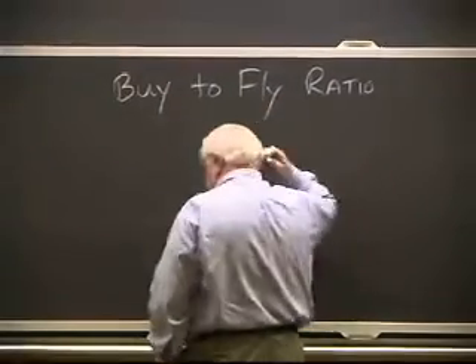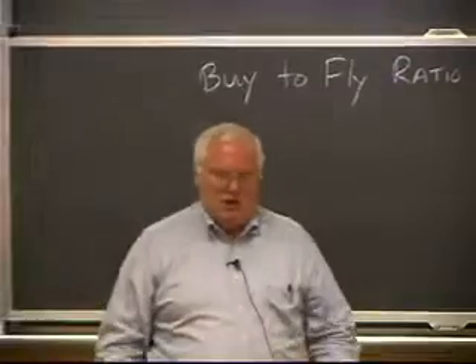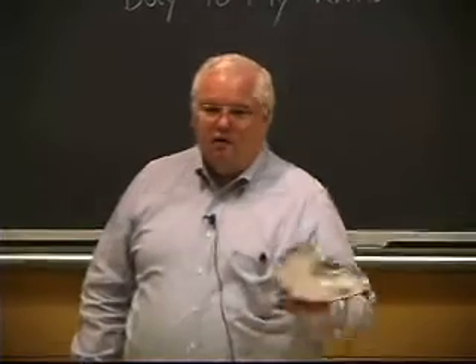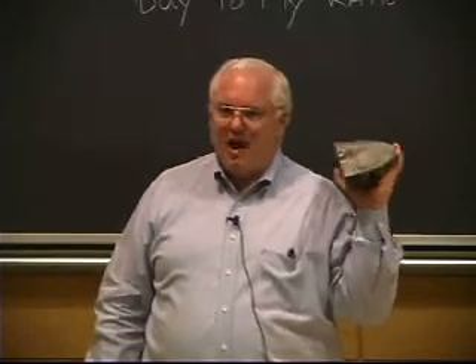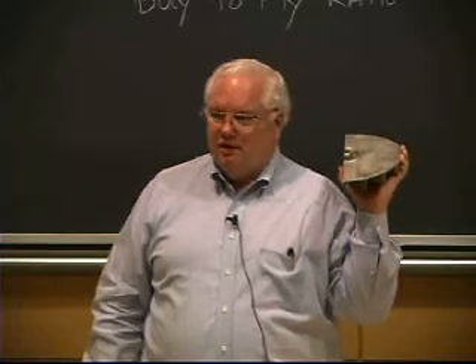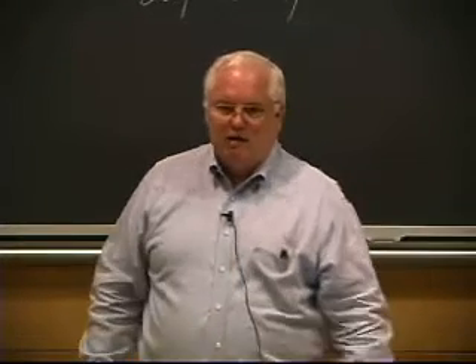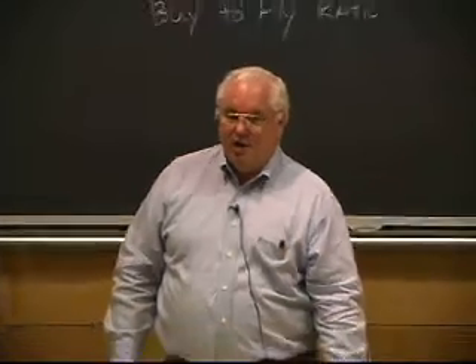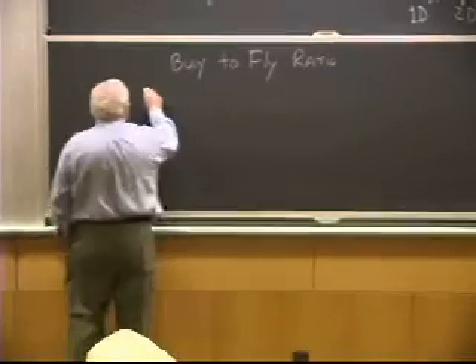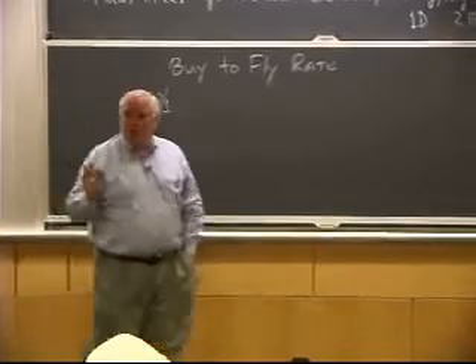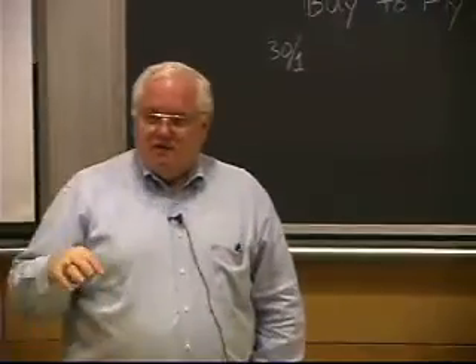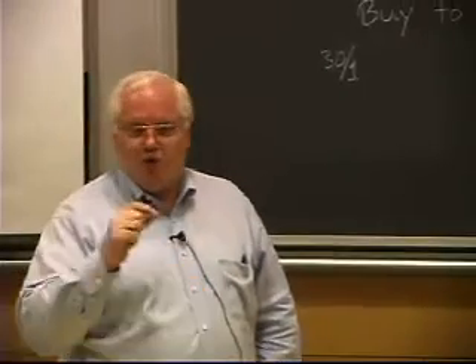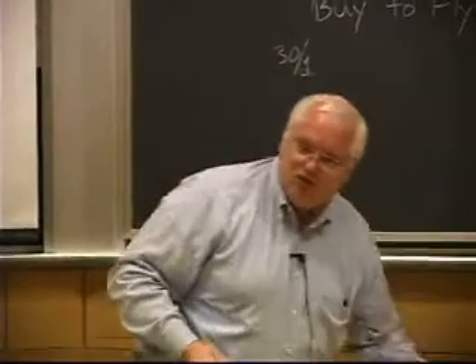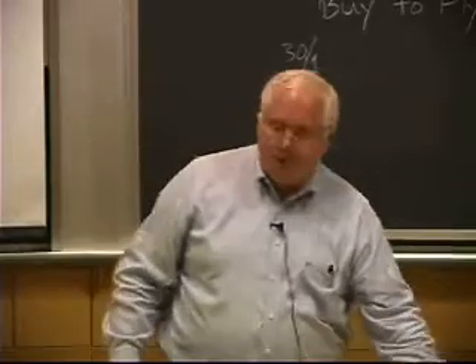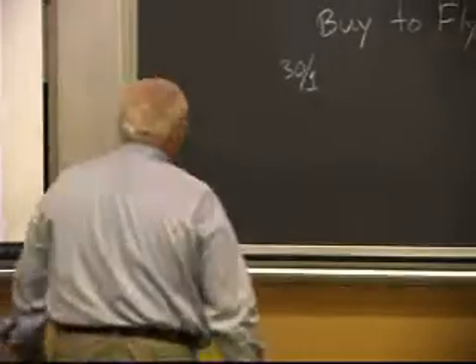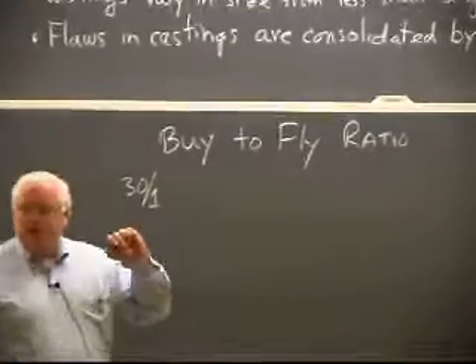back in the early 1980s, I might have to purchase 100 pounds of a superalloy or a titanium alloy for every pound I was going to fly as the final part, which means I'd have to forge it and machine away 90 to 99% of what I had. I think the average for all aircraft parts for the Air Force was a buy-to-fly ratio of something like 30 to 1. There were some parts that were very complex and had very thin sections. They needed the quality of the forging, but they didn't want the weight, because you can't make the forgings too thin, or it's not going to be able to take the operation, or you'd have to go through too many dies, or it'll oxidize on the surface at the high forging temperatures. But the buy-to-fly ratio was something like 30 to 1 as an average.